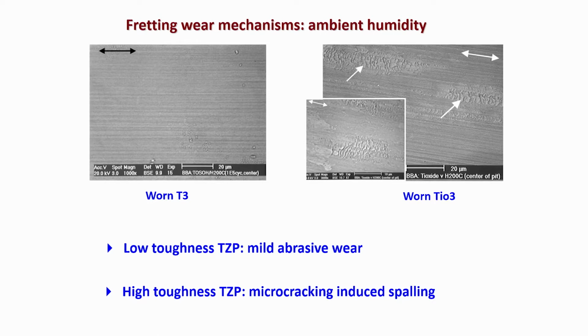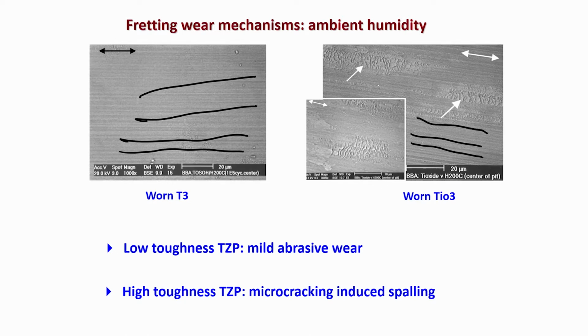for various engineering applications. Now, if you look at the SEM images of the worn surfaces, as I have been repeatedly telling in these NPTEL lectures, we always emphasize discussing and describing the wear mechanisms based on various microscopic observations. So is the case in this present case study. What you see is very clear abrasive scratches in the 3 mole percent tetragonal zirconia, and you can clearly see them aligned towards the sliding direction, or fretting direction, here.